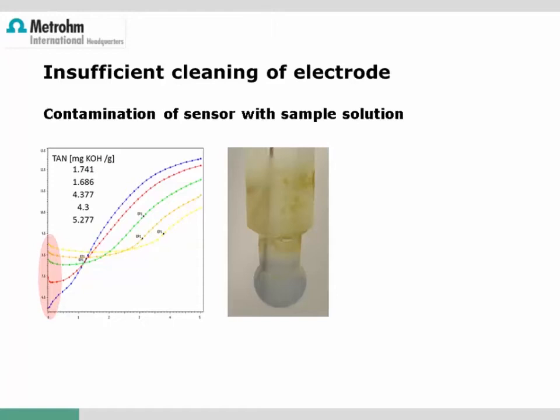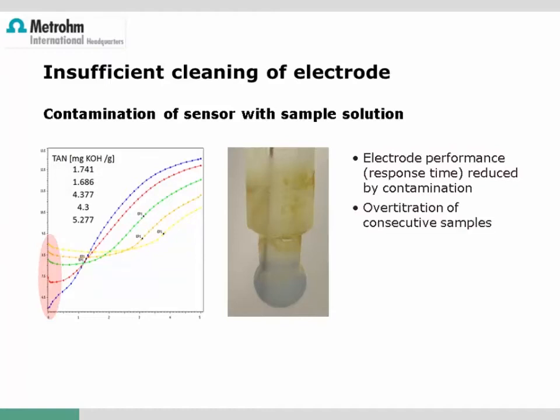Looking at the sensor after these 5 titrations, we immediately see the problem. The sensor is covered with the sample, especially the glass membrane and the diaphragm. This increases the response time so that all consecutive titrations are over-titrated. Means you get too high results. If the sample is always the same, or if you at least know the expected equivalence points, then you could react fast, either by improving your rinsing procedure.